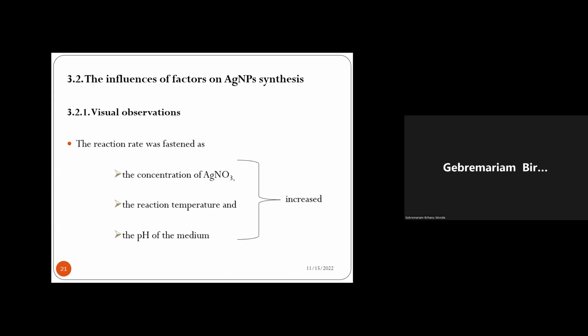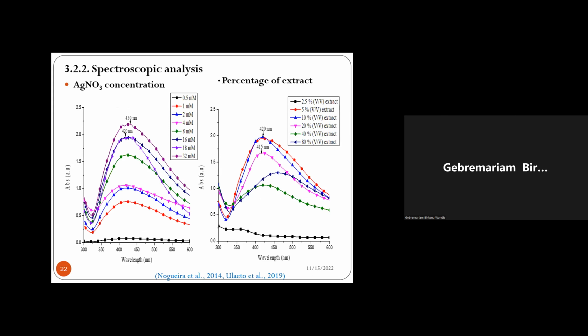And the formation of the pure silver nanoparticles was affected, as we said, by various parameters, and the yield increased when the concentration of silver nitrate or the salts used for the synthesis, the reaction temperature, and the pH of the medium were increased. So these are the graphs that show the different parameters which were controlled and optimized to synthesize the desired silver nanoparticles in good yield.